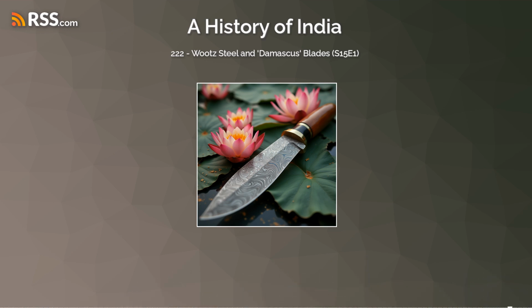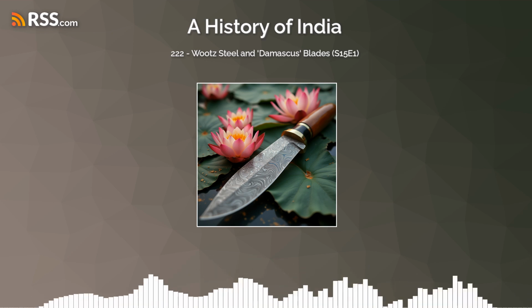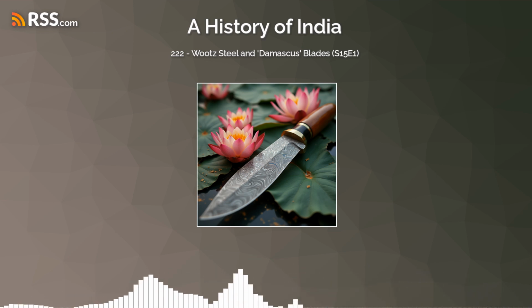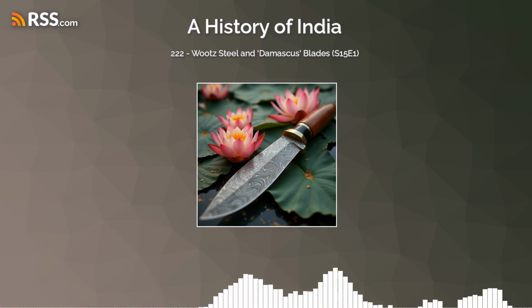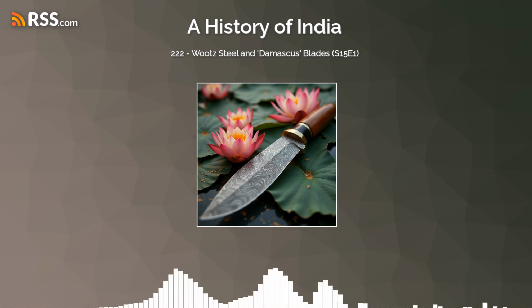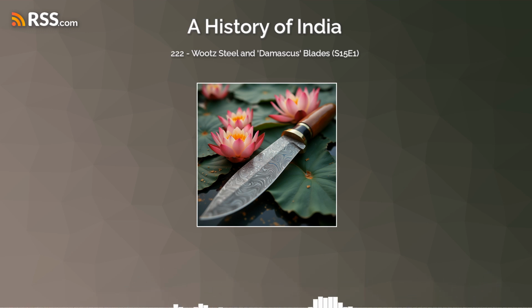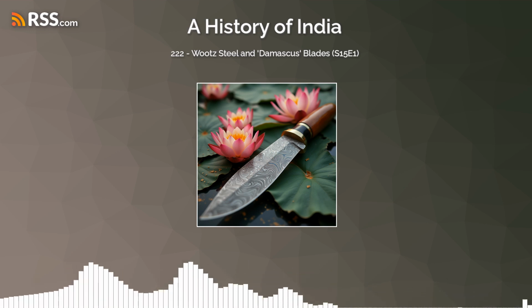Highly refractory. And then you heat that sealed pot to incredibly high temperatures for a long time. The aim wasn't just melting the iron, it was about getting carbon to diffuse into the iron under really controlled conditions, to create a specific high-carbon alloy that would actually melt or get semi-molten inside. Okay, so what went into this alchemical pot? What were the key ingredients for Wootz?